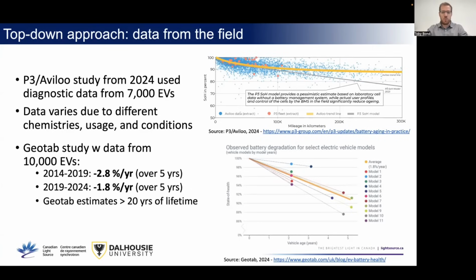And so they estimate we should be getting more than 20 years of lifetime out of that. And they mentioned in their report that this should be more than enough to outlast the lifetime of a typical EV. So what I'd like to stress right off the hop is that we're pretty much already there in terms of the historical data.